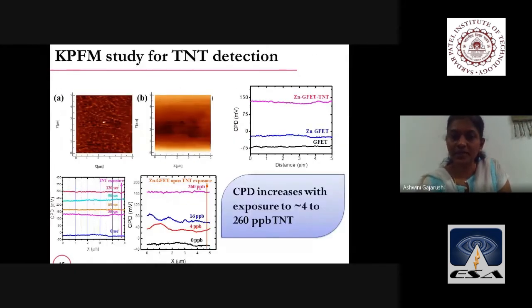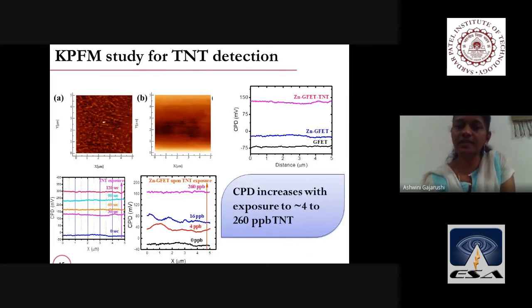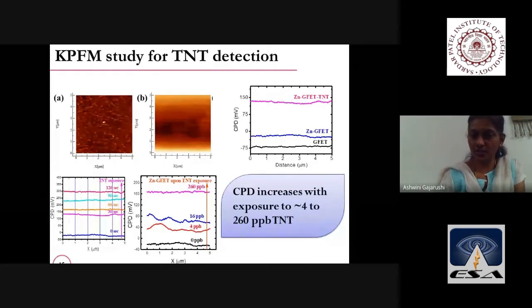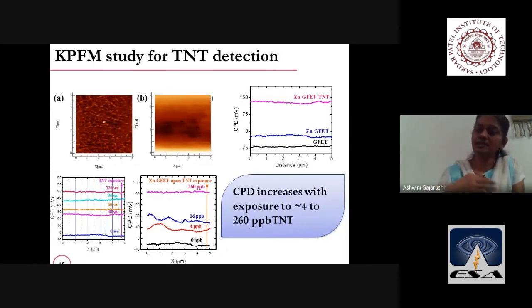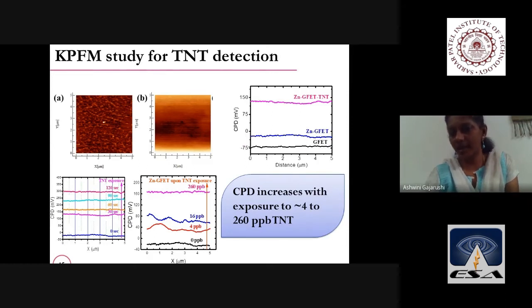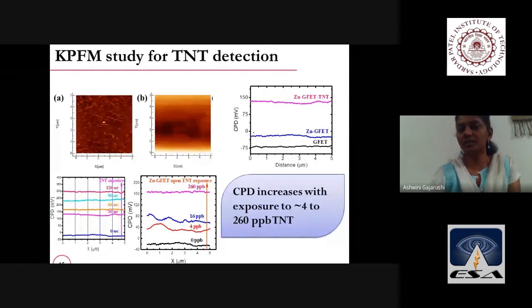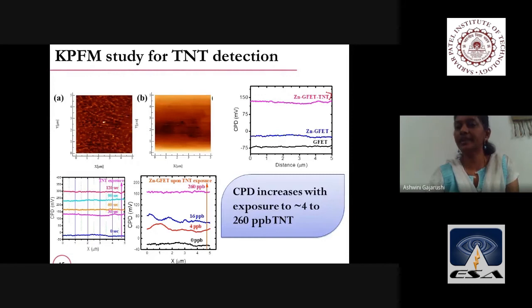Apart from that, similarly, this tool can further be used for the detection of TNT. When the TNT molecules come and attach to this modified graphene, the Zn modified graphene, it again gives us an increase in the contact potential difference. So can you see, the graphene has around minus 75 millivolt, Zn modified has increased to 25 millivolt, and after TNT exposure, it has increased to around 140 millivolt. The CPD value, contact potential difference.